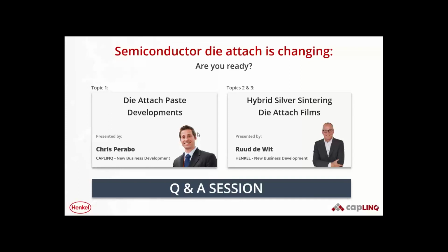I have another question here: does the TG of the material determine the maximum operating temperature of the device? I'll pick that one up. Typically for epoxy materials, I won't say the TG is limiting the operating temperature. The only thing that the TG really shows is when the material goes from that harder phase to the softer phase. A number of properties change at that time, one of them being the coefficient of thermal expansion. It goes from your alpha 1 to your alpha 2 at your TG. Also, the modulus goes from a higher modulus to a lower modulus, typically at the TG. That's really the only thing that the TG is definitely going to tell you.